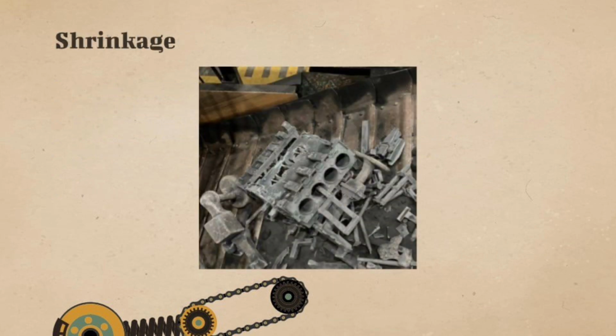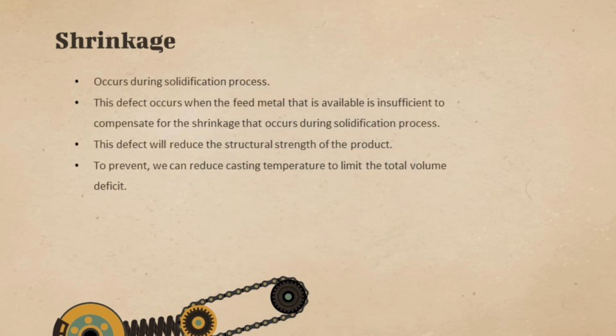Next, we move on to the defect of shrinkage. Shrinkage occurs during the solidification process. This defect happens when the feed metal that is available is insufficient to compensate for the shrinkage that occurs during the solidification process. This type of defect will reduce the structural strength of the product. In order to prevent this defect, we can also reduce the casting temperature to limit the total volume deficit.